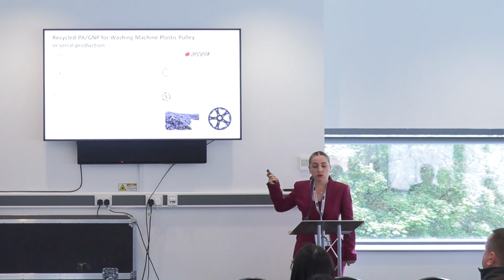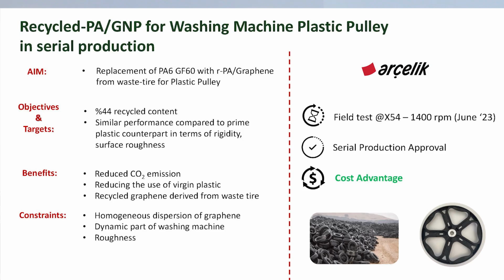Also, this is now in serial production. Arçelik, now Beko Global. Most people use their white goods in their houses. Here, what we did is use recycled polyamide with glass fiber. In the serial part, they are using a virgin polyamide. Now we change, and we add 1 weight % graphene, and then we keep the mechanical integrity despite some loss coming from the recycled plastics. So we prevent that, and we provide a cost advantage. Now the formulation is under serial production, and we will produce 200 tons per year next year with this formulation just for this part.